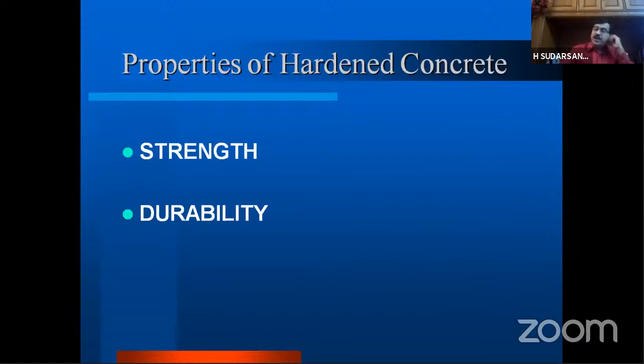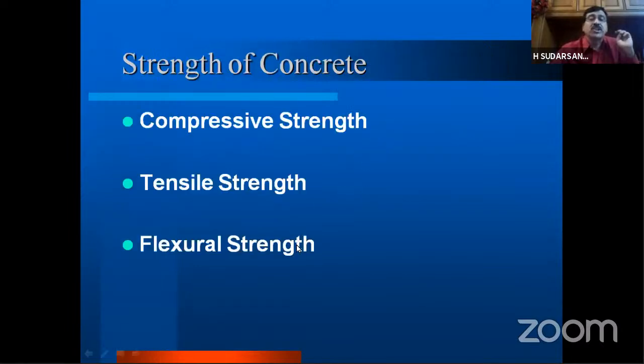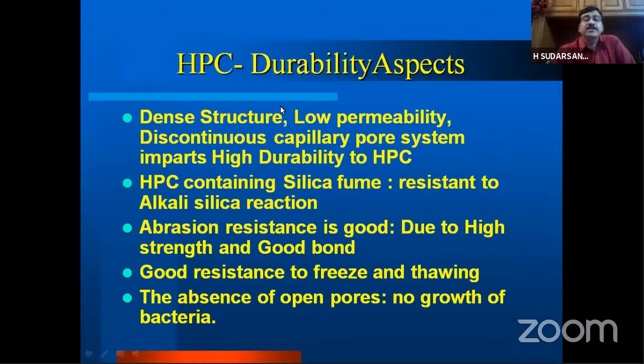The important properties of hardened concrete are strength and durability, with different types of strengths: compressive strength, tensile strength, and flexural strength. In normal concrete, we focus more on compressive strength, but in high performance concrete, we have to consider compressive strength, tensile strength, flexural strength, as well as modulus of elasticity. The durability aspects also we have to focus on. Alkali silica reaction is to be avoided. Maintain good abrasion resistance and good resistance to freezing and thawing. Reduce the open pores so that there is no growth of bacteria. To achieve all this, we have to have a dense structure, low permeability, and a discontinuous capillary pore system. So there should not be continuous capillarity. This gives high durability to high performance concrete.